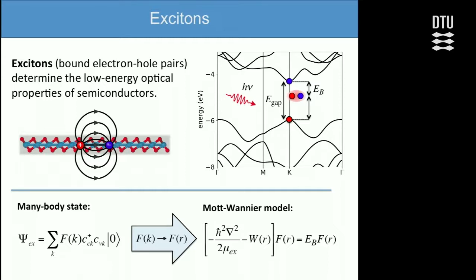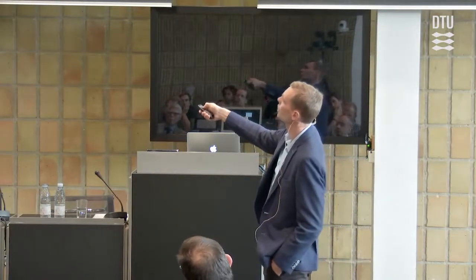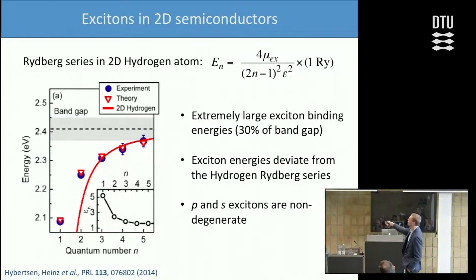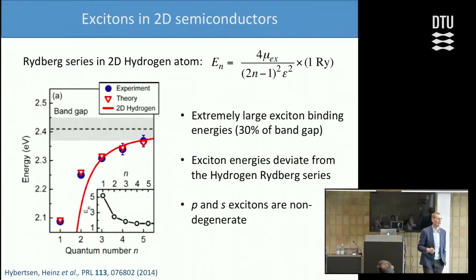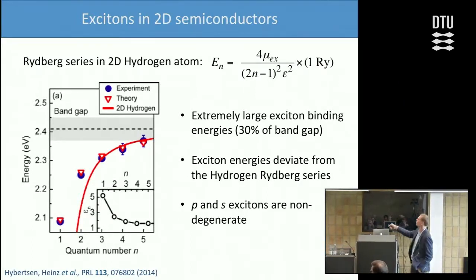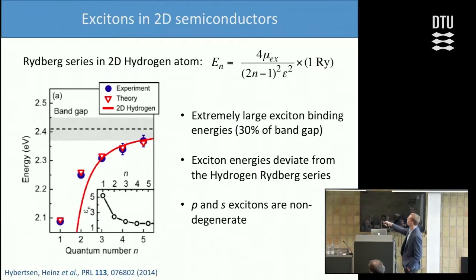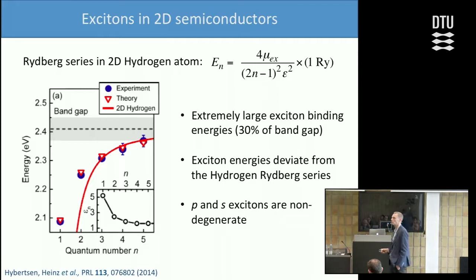The point is this doesn't work in 2 dimensions, and let me show you why. Here are some measurements of the 5 lowest lying excitons, the 5 lowest energies of the Rydberg series in tungsten diselenide that have been measured. Here's a fit to a hydrogen atom, and you see that fit doesn't work very well.